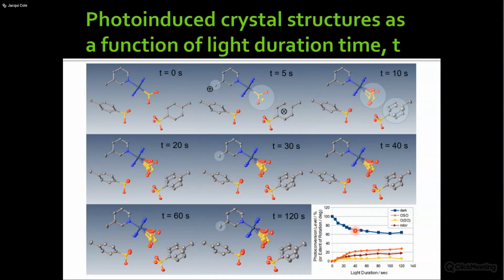And this graph here is essentially showing you, having refined each of those individual structures at each of those time points, what's happening to the photo conversion level of the different components that are changing in response to light. So the dark state in blue is really decreasing in population from 100%, which you'd expect, because you're seeing the formation of these photoisomers. You can see that goes down to, in this case, about 80%. So in other words, 20% photo conversion, and then it makes sense. There's a symmetry involved in this, of course.